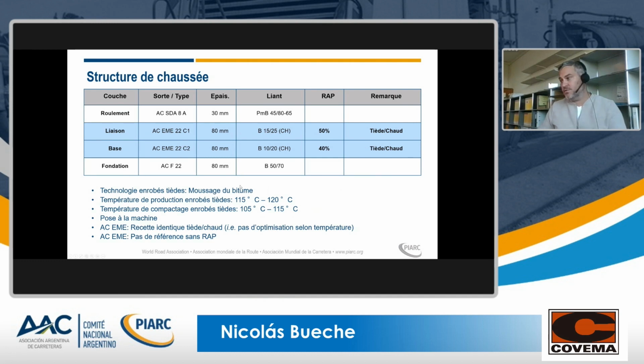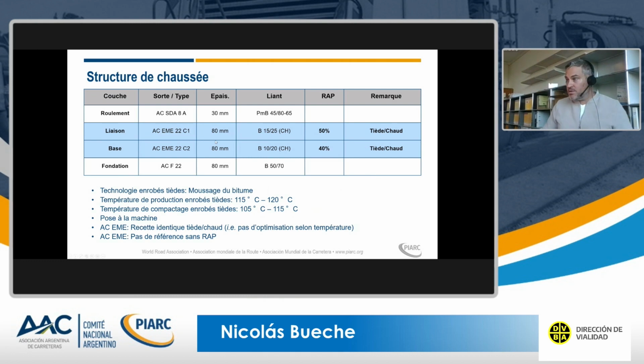Production temperature, 115 to 120 degrees, compaction temperature between 105 and 115 degrees. All the asphalt has been laid using a machine, nothing by hand. And which is also important, we used the same recipe, the same recipe for the reference hot and warm mix asphalt. So there is no mixture optimization. So important, we made these 2 layers with warm mix with 50 and 40% reclaimed asphalt.